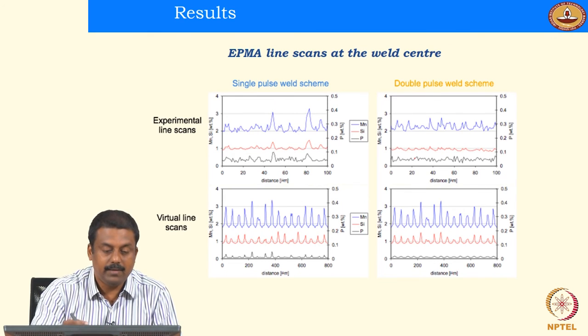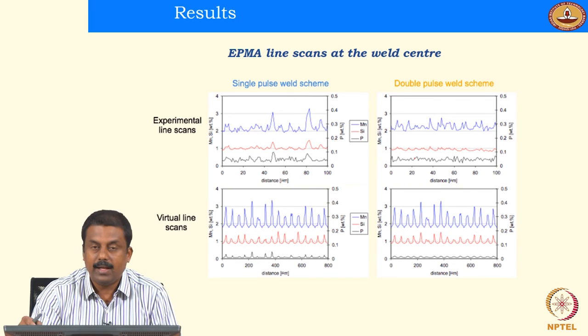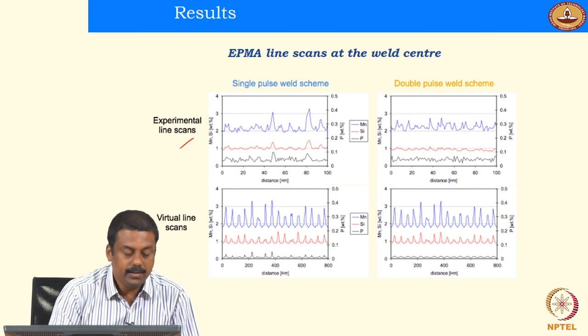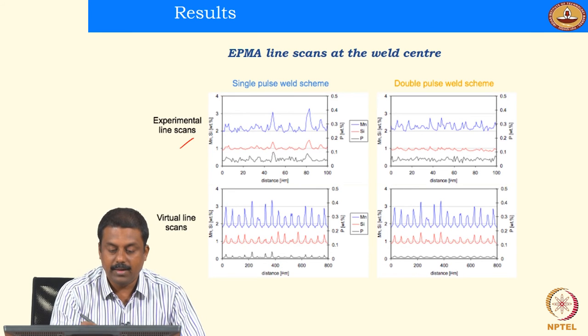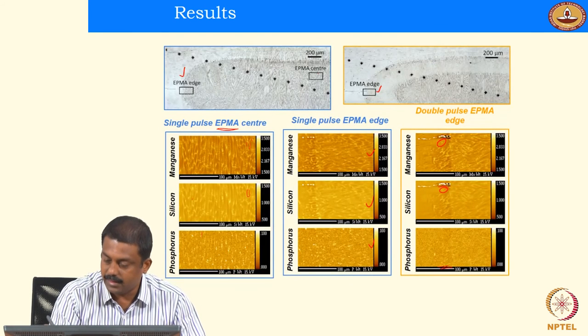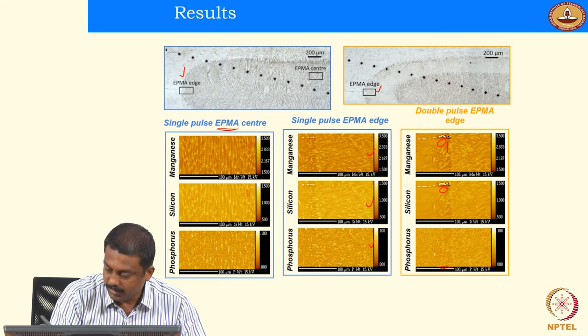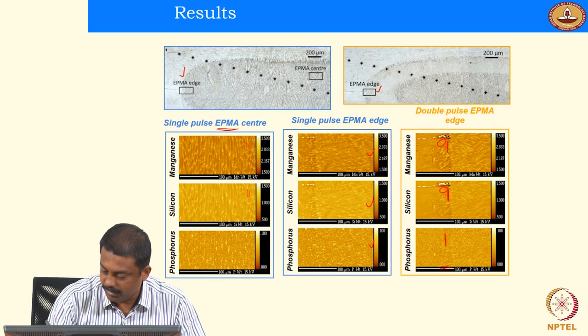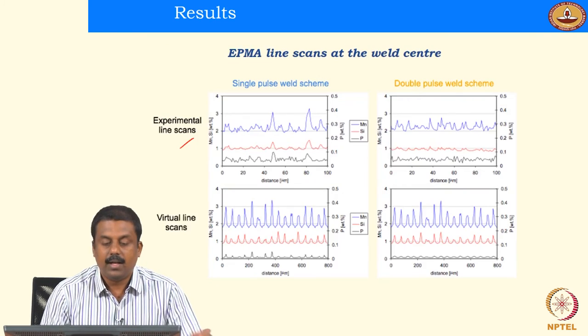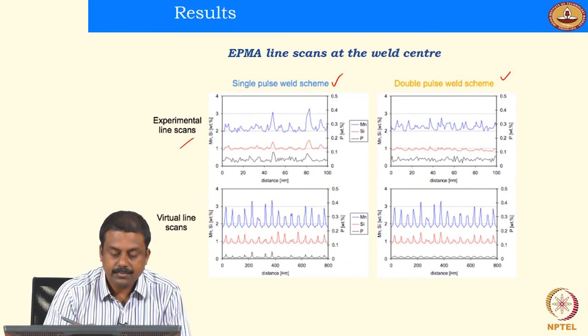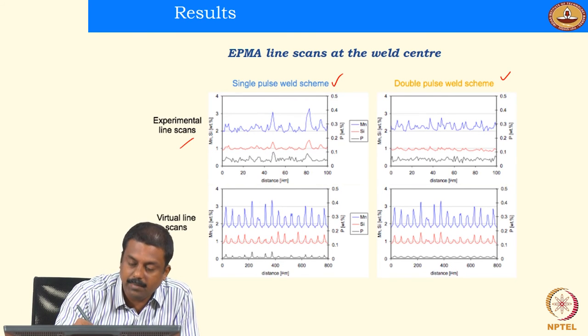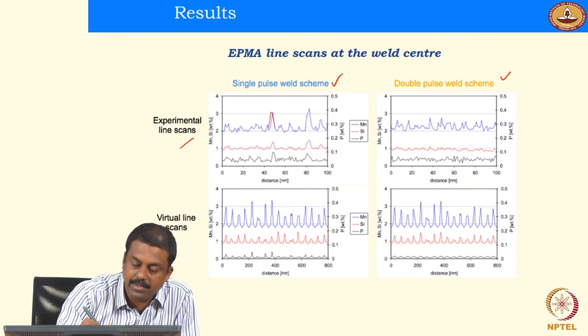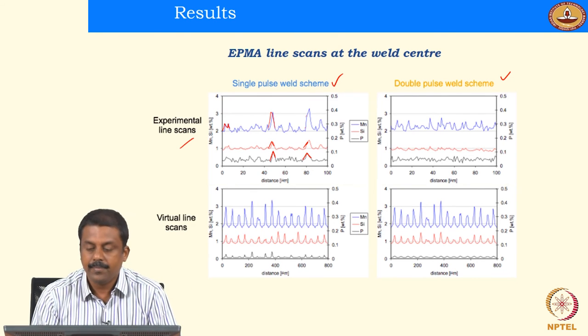it also became clearly seen from the EPMA line scans at various regions. So this is the experimental line scan during single and double pulsing. So for example, a line scan is carried out somewhere here, somewhere over there, somewhere over here, after single and double pulsing. You see clearly the manganese is segregating in some regions. Those regions are all the boundaries. Similarly, silicon and phosphorus are segregating at the boundaries.